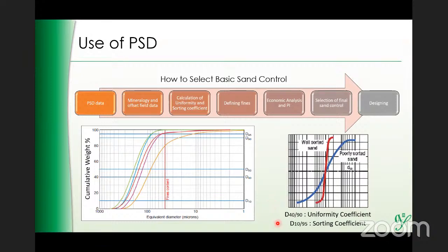And the third parameter we look at is the fines content. Fines content are the particles which are below the size of 44 micron. So if your fines content is greater than 10%, then it's very difficult for you to stop these fines. And if you stop these fines, you will end up with plugging your screens.